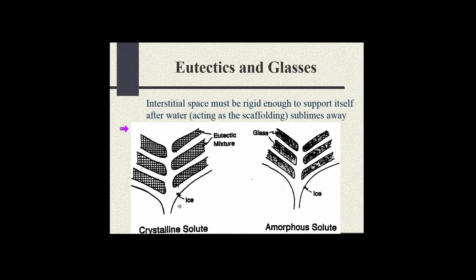So I've got a little diagram here showing you, again, the phase separation. These are the ice channels. And we like nice wide ice channels because they provide a good conduit to get the water vapor out of the product. And here's the interstitial space. Now, in this case, it's a crystalline solute, so it forms the eutectic. In this phase, it's a glassy phase, which forms the glassy amorphous phase.